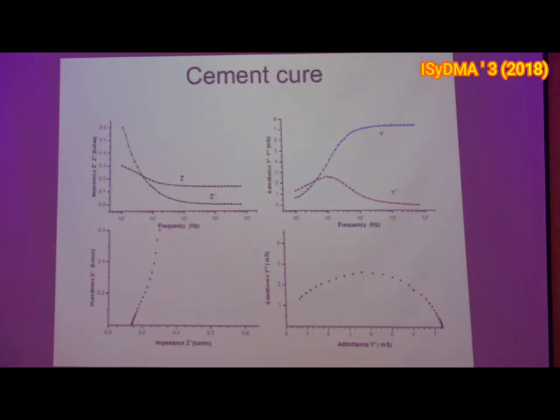So this is how the curves are presented. This is the real and imaginary part of impedance as a function of frequency for a given day and at room temperature. Here we have nothing interesting. We cannot see any peaks, nothing at all. So we don't know if there is any relaxation process. But when we invert this and calculate the admittance, we can see one peak here in the imaginary part that corresponds to the inflection of this real part. So this is typically a relaxation process again.